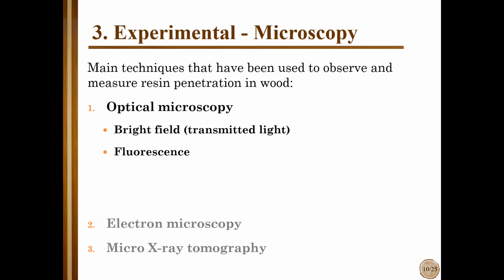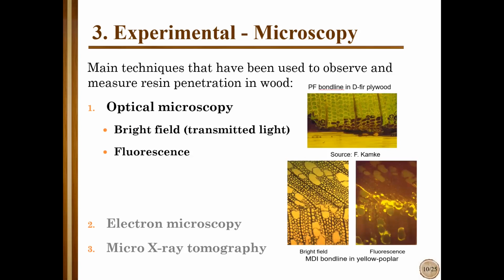So now I will turn to one experiment where we used bright field and fluorescent microscopy. Let me tell you that some of the adhesives we use, like phenol formaldehyde, are easy to see under optical microscope. But some others, aminoplastic adhesives like urea formaldehyde or melamine formaldehyde, or on another side, other adhesives like isocyanate adhesive, are transparent when they cure, and practically you don't see them under bright field optical microscopy. Here you see two photos, and on this left one, you cannot actually detect where the adhesive is. If you use fluorescence microscopy, you can easily detect those adhesive spots. So today, I'm mostly going to talk about fluorescence microscopy.